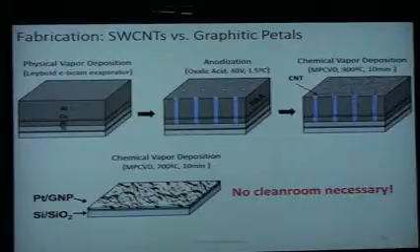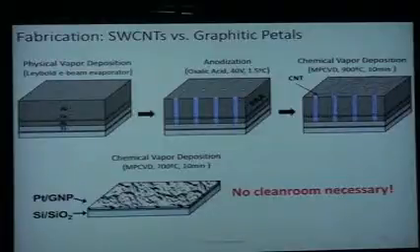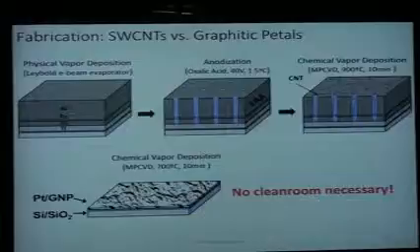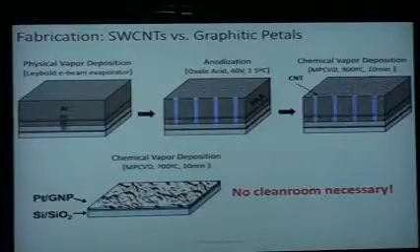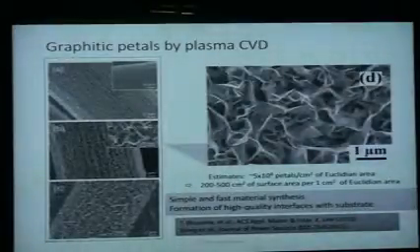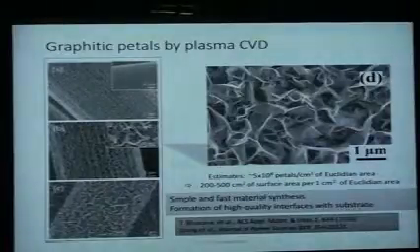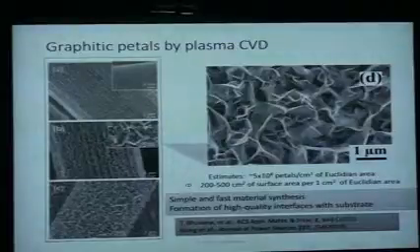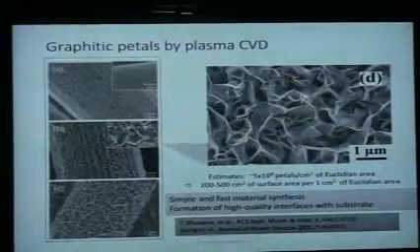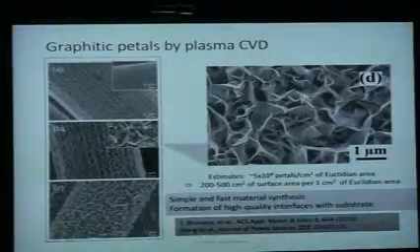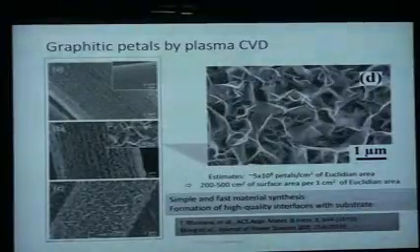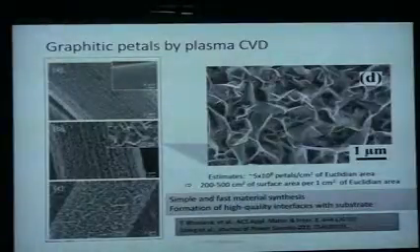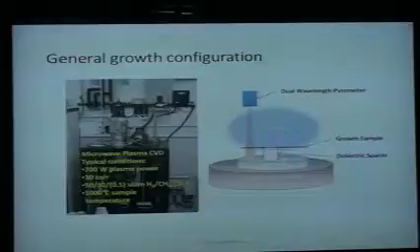On the other hand, these petals don't require any catalyst and don't require any metal to be deposited beforehand—they just come out. That's a good contrast. We use plasma CVD to grow these petals, and we have nearly a billion of them per square centimeter. Each edge is about a micron or so. It's simple and fast to make, and this was done about five or six years ago. We grow them in a microwave chemical vapor deposition system.